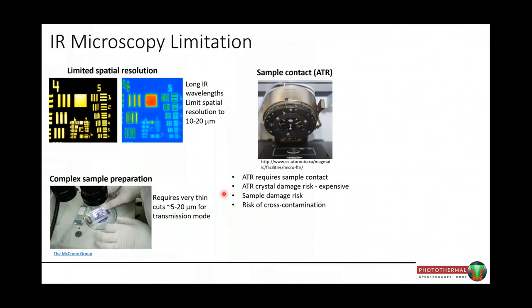Alternatively, you can use attenuated total reflection, but it requires contact with the sample where you risk damaging the ATR crystal, which is expensive, and you also risk cross-contamination as you move from point to point on the sample. Ideally, what one would like to do is simply bounce the mid-infrared radiation off the sample and look at the reflected light, like you would do with Raman and near-infrared spectroscopy.